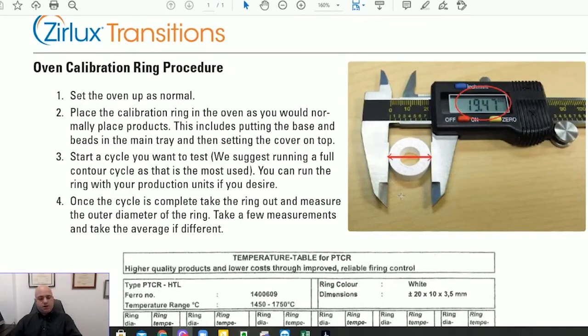Again, this is a green state zirconia that is manufactured to have a very specific shrinkage that is dictated by the temperature to which it's subjected. So again, this is a cool zirconia at this point, and it is one-time use. Once it's sintered, you're able to take this to a digital caliper and see the exact numbers of the diameter. Those numbers correlate directly to the true temperature within. So if we look at this document, 19.47 correlates to 1506 degrees Celsius inside your furnace.